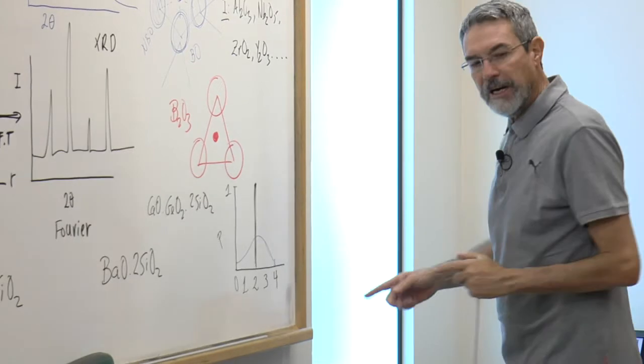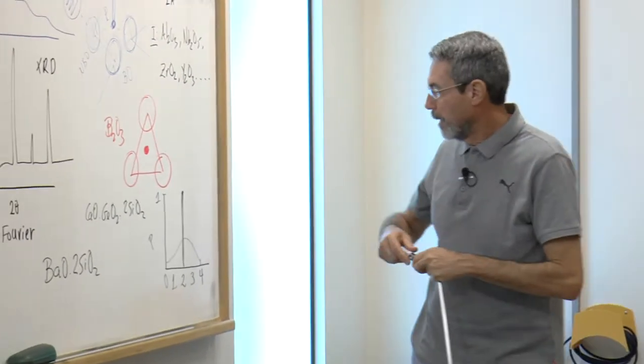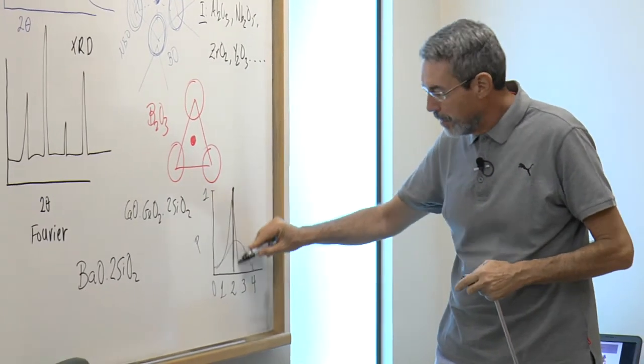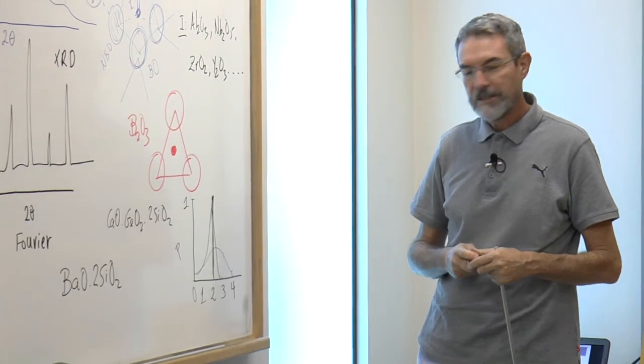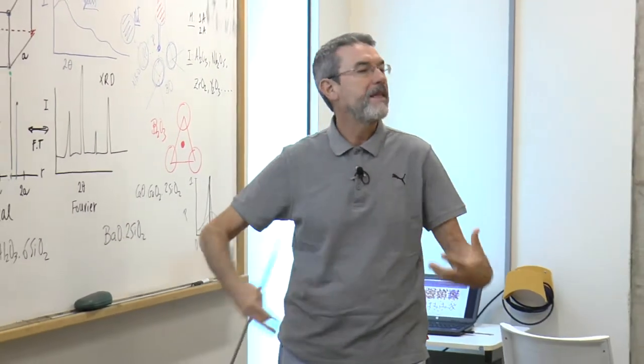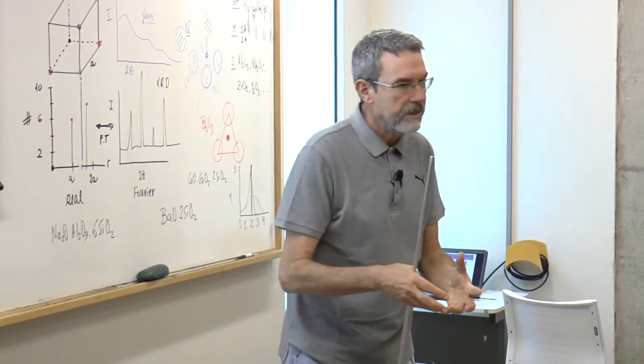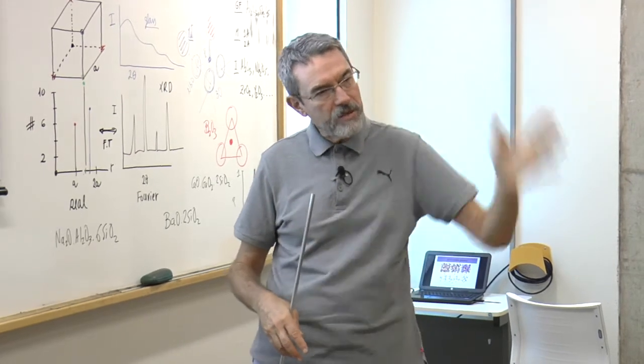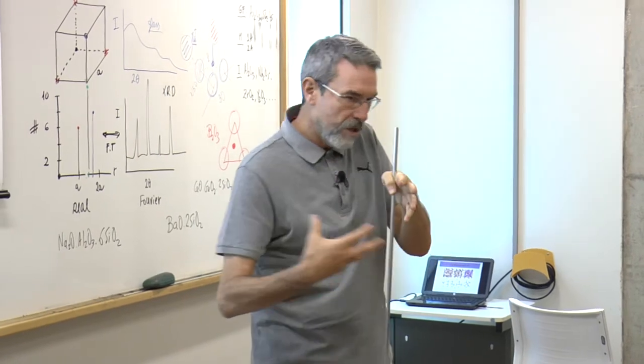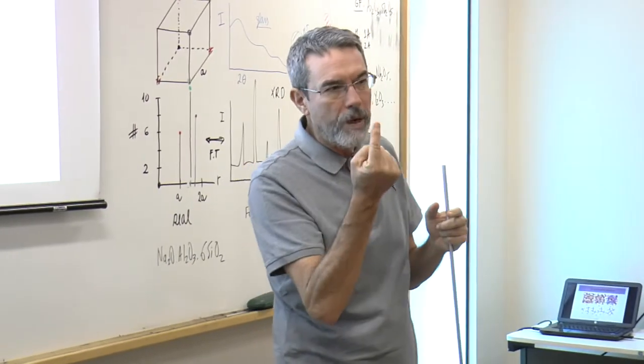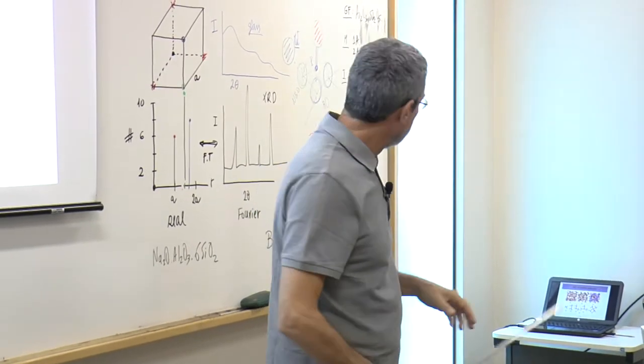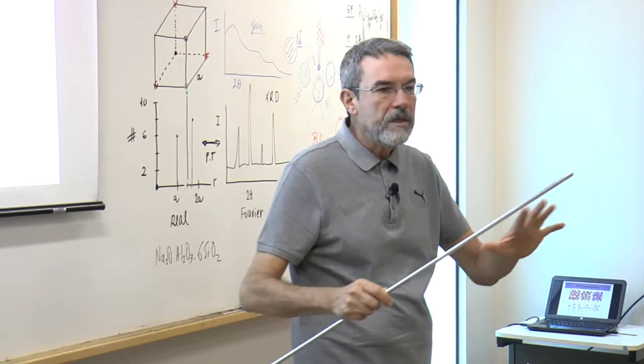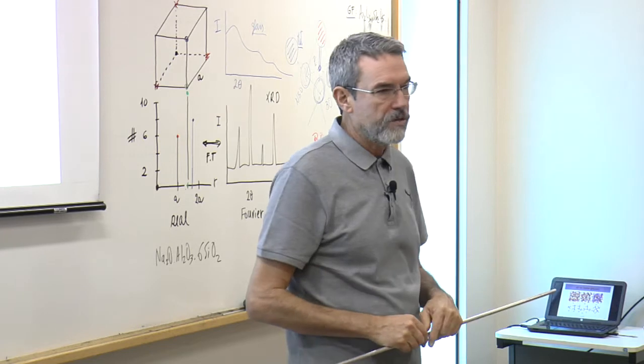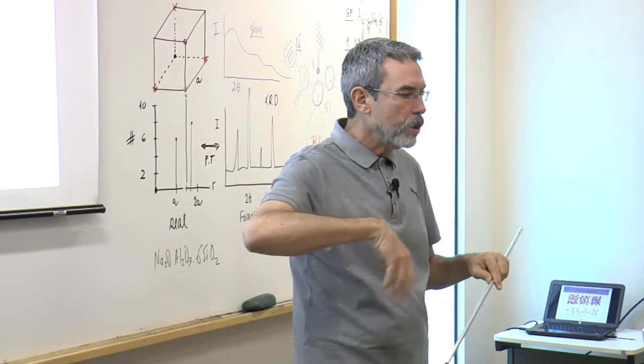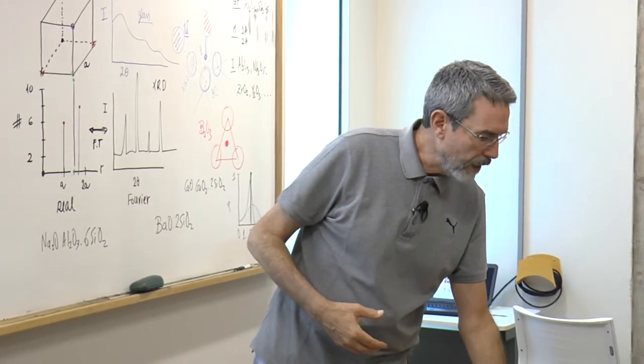And this is very interesting because the more the glass distribution approaches the crystal distribution, the more similar the structures are. This is one way to see the similarity of that particular feature between the structure of the glass and its isochemical crystal phase. There are many other features of the glass structure. This Q distribution is only one of them. This is like the intermediate range order or medium range order of the glass structure, but you need other information to be able to really construct the structure of a glass, not only the QN distribution.